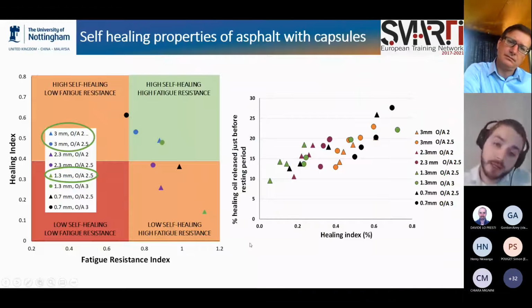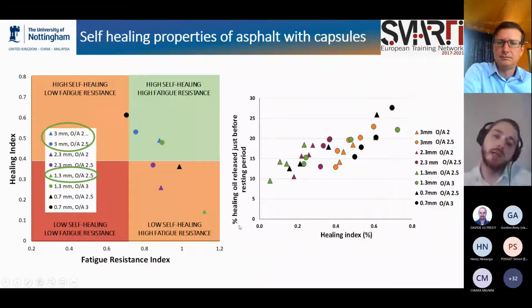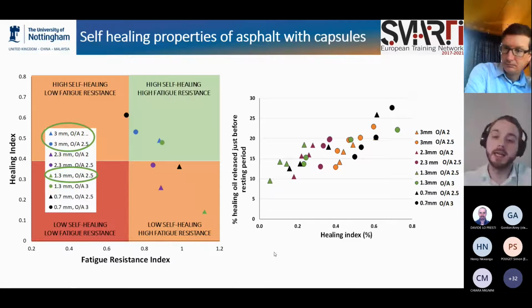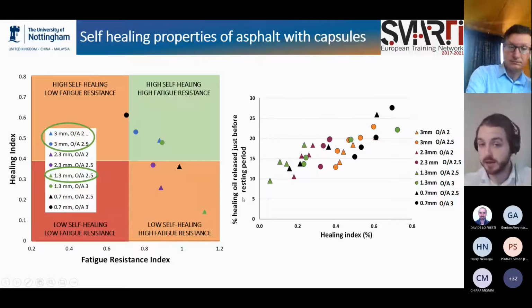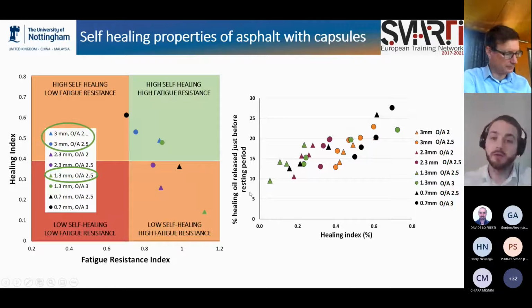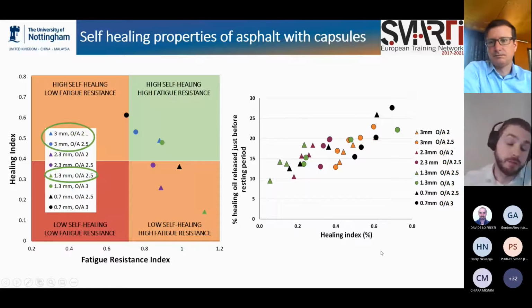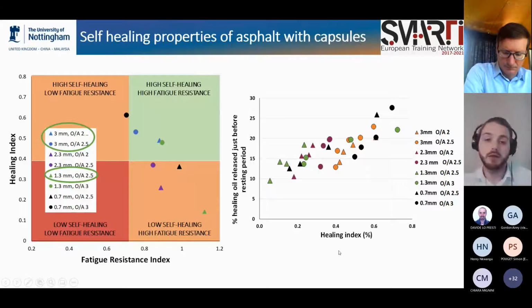This graph represents the self-healing oil, I mean, the percentage of the healing oil released just before the resting period. So basically, it's the amount of oil released related to the healing index, and we can see that in the samples where the healing index was higher, we also find a high amount of oil released, which makes sense. But it was something to be confirmed.